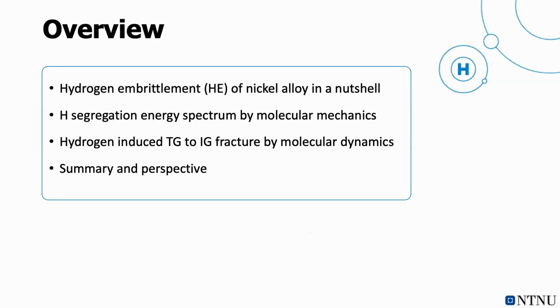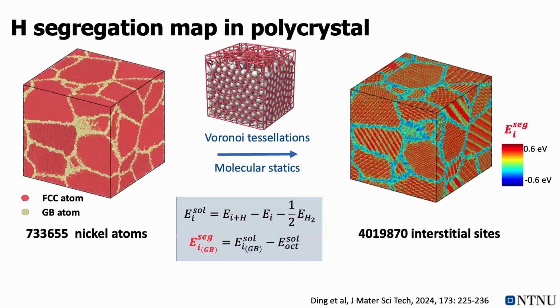Today I will first talk a little bit about the hydrogen segregation energy spectrum by molecular simulation, and how hydrogen induces the transgranular to intergranular fracture transition by molecular dynamics. Then the summary and perspective. As many colleagues have shown, hydrogen embrittlement in metallic materials is really a multi-scale problem. Many of us focus on the continuum or mesoscale level, on how the property is degraded when hydrogen enters. But at the root, at the molecular and atomic level, how hydrogen interacts with the metallic atoms, especially with specific microstructural features of the material, is still questionable.